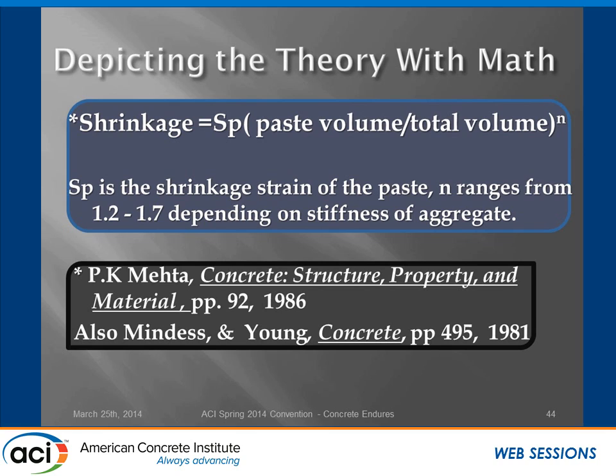Here's some math to depict the theory. These are out of two widely used textbooks on concrete, widely used when I was in college. The shrinkage of the concrete is equal to the shrinkage of the paste times the volume of the paste raised to a factor n. n has to do with the stiffness of the aggregate. And the whole theory comes together right there. It came together back in the 1980s, however long before they published that.